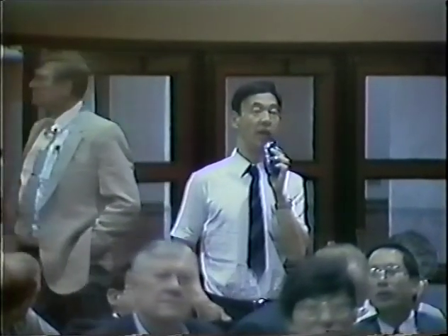Is it working? Tani Hata from RIKEN. About the deposition of lithium. Our analysis says that it's not a deposition on the surface, but diffusion into the palladium. And what we observe is it's really diffused into at least 2 microns, and its distribution is almost flat. So my guess is that the lithium is really diffusing into palladium after electrolysis, more than 2 microns.